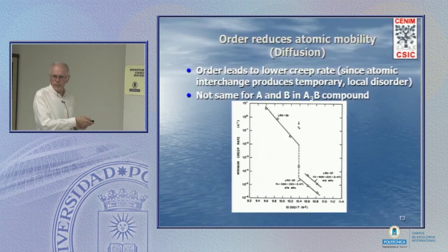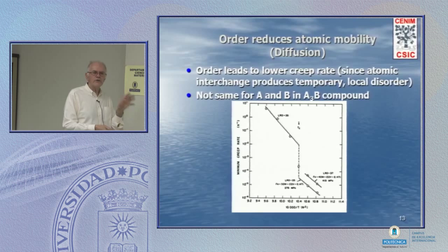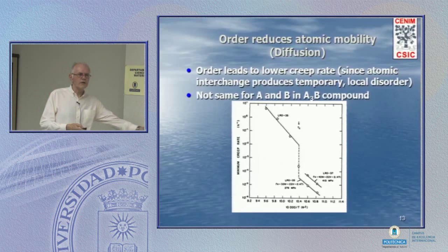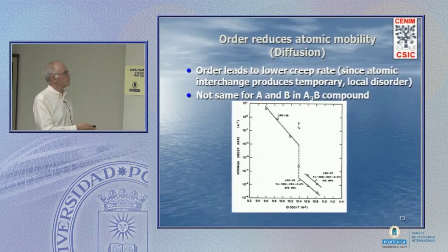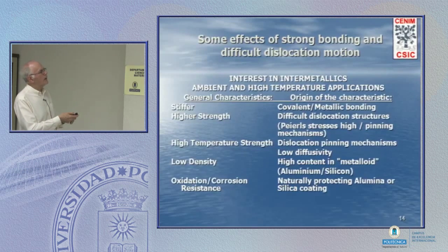Here's an example of creep under conditions where the creep rate depends on the diffusivity. So this is creep rate as a function of reciprocal temperature. At low temperature, we're highly ordered and diffusion is slow. When I reach a temperature where this alloy disorders, then suddenly the diffusivity, and so the creep rate, increases by 2 or 3 orders of magnitude. Anything that depends on atomic movement will be delayed inside the ordered state. And again, if I'm looking at a high temperature application, lowering diffusivity as well as making dislocation nucleation difficult is good news.